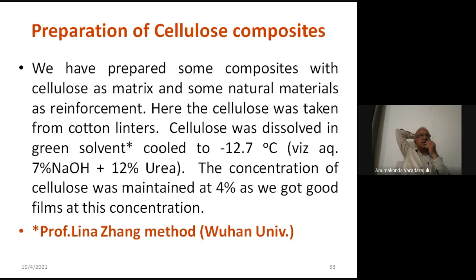Industrially they used cuprammonium salt and carbon disulfide, which are both carcinogenic. So now they are not recommended, but we developed our own solvent with safe chemicals, for example, 7% sodium hydroxide and 12% urea in water, and then we cooled it to minus 12.7 degrees Celsius. You may ask me one question: will it require any special gadget to cool it to minus 12.7? If you have a deep freeze, it will go up to minus 15 degrees. So if you have a freezer in your laboratory, you can keep this beaker in the deep freeze, and in 1 or 2 hours, the temperature comes to around minus 12.7.